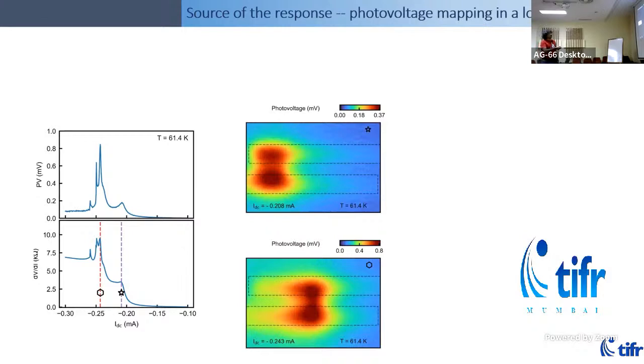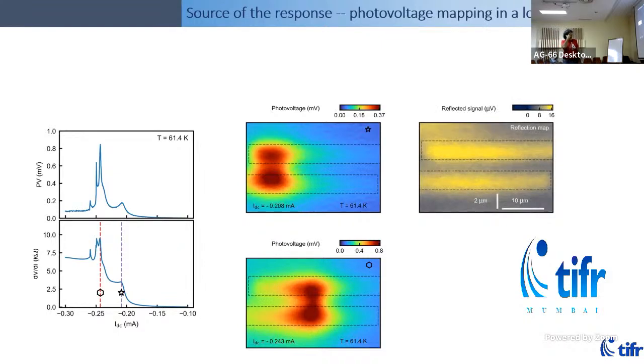And depending on the bias point, this demonstrates that it's not a spatially uniform response to the device. From the electrical response, if there are phase slips or hotspots formed inside the system, they are sensitive to external radiation, and you can detect them. So if you bias it at different points, different parts of the detector, if you have an extended detector, will sense the bolometric response from the incoming light that you have.